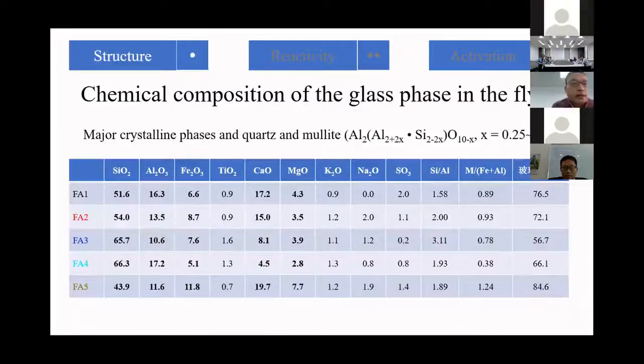And the other SCM is the fly ash, and the fly ash shows the major crystalline phases are quartz and mullite, but mullite is just a general description. Different fly ashes have different chemical compositions and also structures, and the glass content of these fly ashes ranges from 56 to about 85%. From this glass chemical composition, it can be seen that it is constituted mainly of silicon and aluminum with a small amount of calcium, magnesium and other alkali cations.